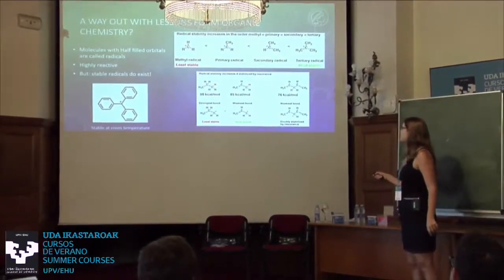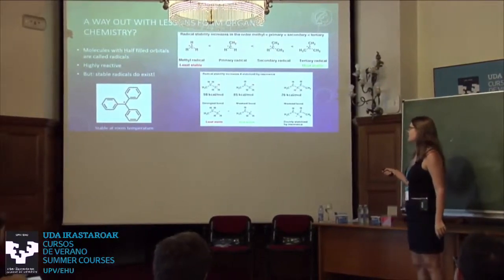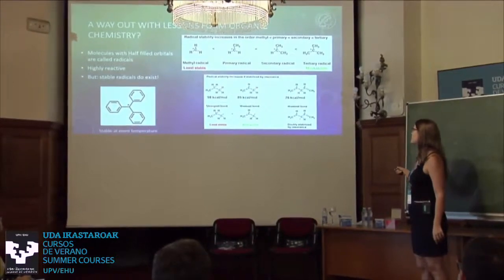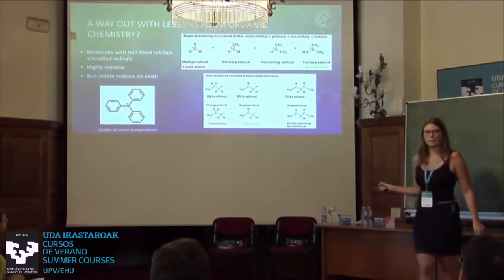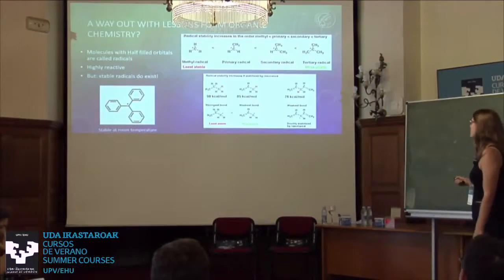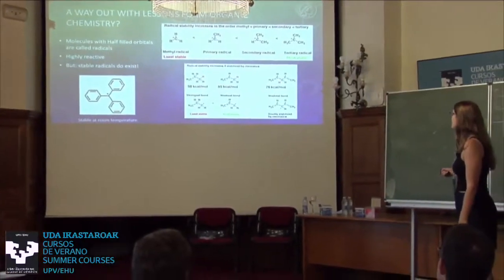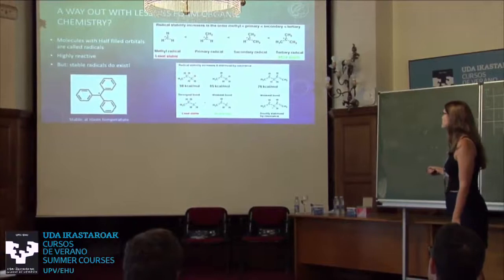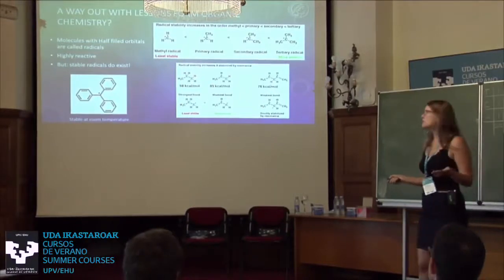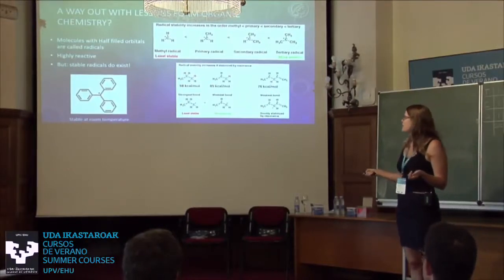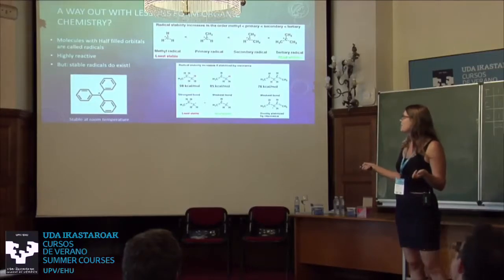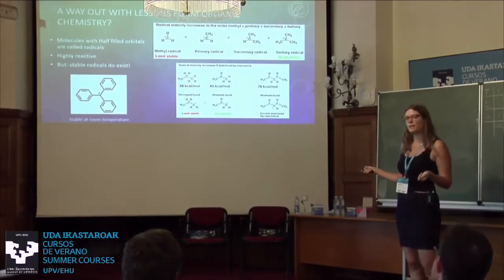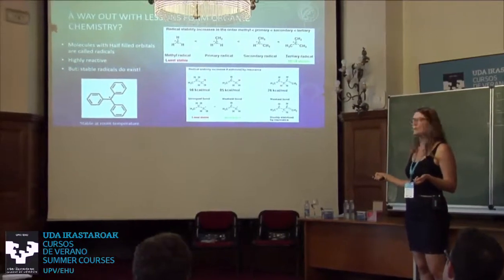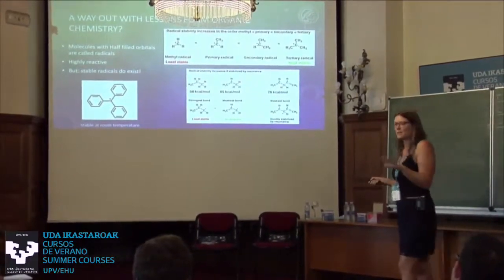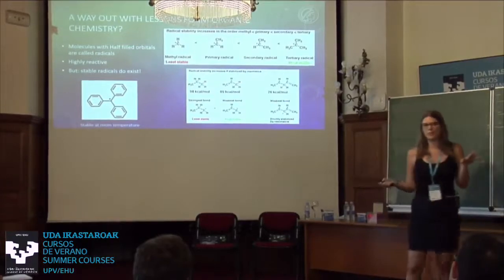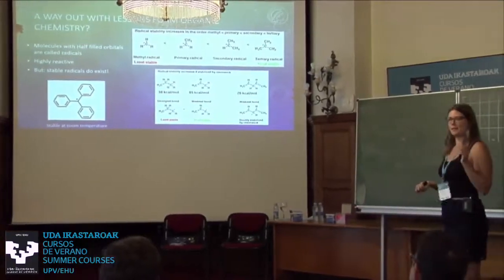A carbon atom with just H's, the radical is super unstable. If you put some organic residues on it, it becomes more stable. And then you can also put residues where the electron can be delocalized over those double pi bonds, and then it becomes even more stable. And then finally, you can make a radical like this, where this single electron can now hop around all those sites, and this compound is actually stable. This radical is stable at room temperature. I mean, it's not that stable, don't get me wrong. If it sees a little bit of oxygen, it's dead, but at least you can handle it for some time.